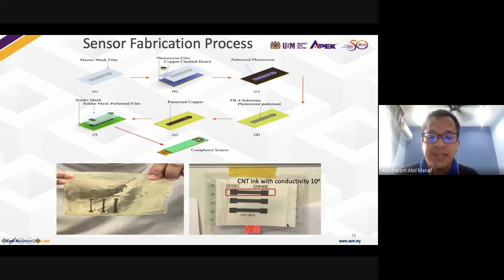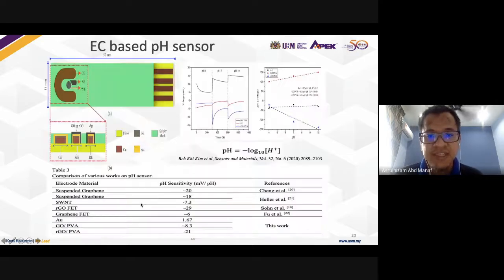We bought that bandage from a pharmacy and printed CNT ink on it. That was our first test, on the conductivity, and we also tested on gelatin, just to play around. We wanted to see the adhesion between the ink and the substrate. We also developed the pH sensors and published in Sensors and Materials, but we still suffer in terms of sensitivity. This is still ongoing, on the ink formulations.